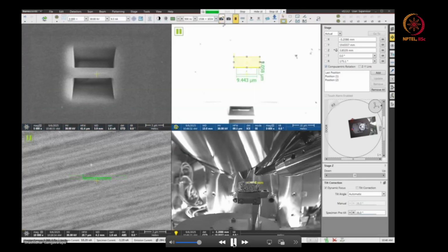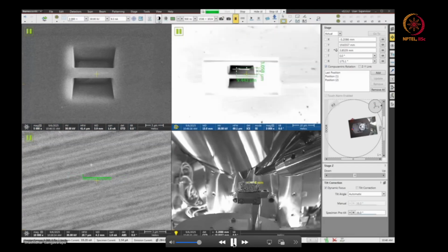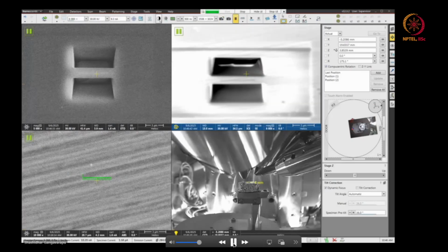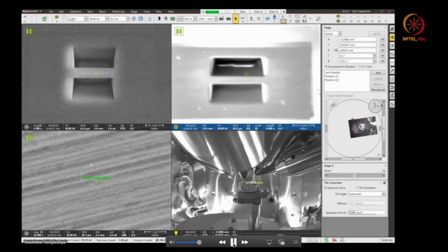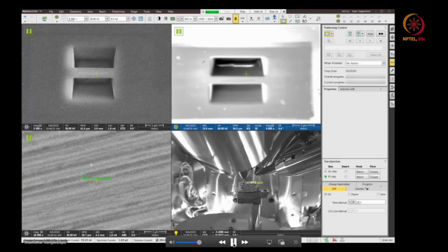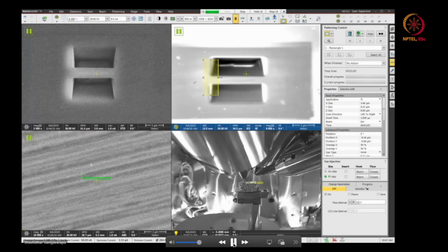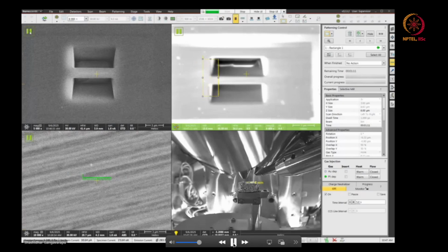Now the next step is to cut at the left side. We cut on the left side to bring in our manipulator for lifting out the sample. So next I will draw a rectangle pattern at the left side, and the dimension is around x is 3 or 4, and y should be the entire height, around 8 to 10, and z is around 6. The pattern should have a left to right scan direction, towards the sample always.